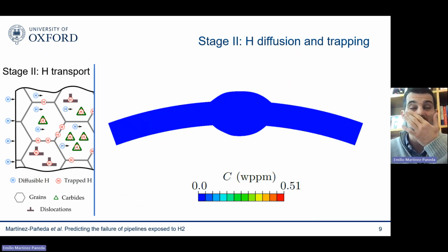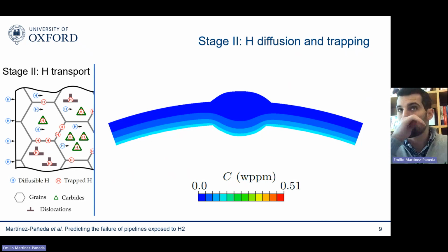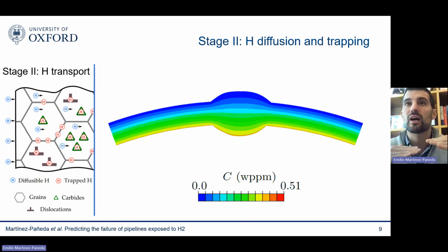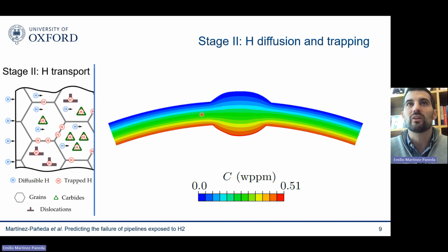So this is a representative result. What you see here is a pipe that is being exposed progressively to a rising hydrogen pressure, pure hydrogen, and you can see how the hydrogen in the boundary increases, and you can also see how, as time goes by, the hydrogen distributes within the pipe. So you see you have hydrogen coming in the inner part. This is a weld within the pipe, and then this hydrogen equal to 0. The hydrogen is free to leave the outer surface, so you get this gradient in hydrogen concentration. So this is the type of thing that you can get with these models. Again, relying only on parameters that are very well understood, that have a clear physical meaning, and that we can independently measure with experiments.